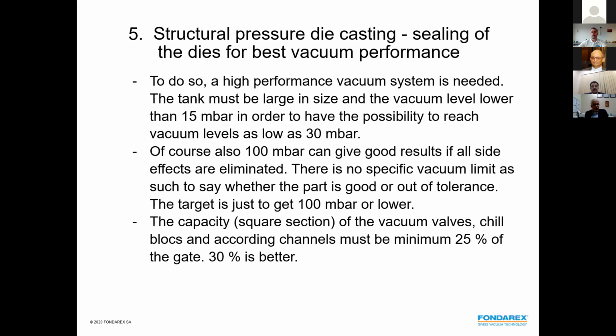Therefore, in structural casting, a lot of people talk about vacuum levels of maybe 50 millibars, maybe 30 millibars. Therefore, inside the vacuum tank, the pressure may be 15 or maybe even 10 millibar. That means the vacuum pump has to be a little bit larger to really guarantee very low values in the tank. But 30 millibars is not always the target. We have made many, many good castings with 100, 120 millibar. Why? Because in most cases, it's more important to have the right characteristics and right parameters than the best vacuum level.